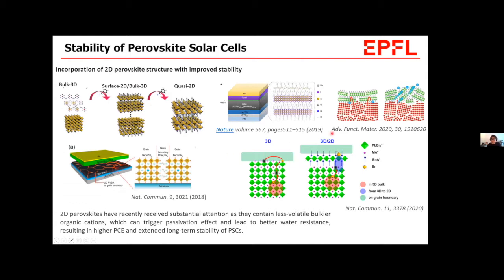So yeah, if we compare these two systems, 3D and 3D with 2D perovskites, about the ion migration, we can see the possible pathways of this ion migration in these two systems. So the diffusion barrier energy within this 3D work region would be similar in both systems. But however, the barrier energy for this ion diffusion becomes highly different when it comes to the region of grain boundary. In 3D perovskite, the ions can reach this grain boundary without being required to diffuse across the 2D perovskite barrier layer. So it's kind of a free path, it can just migrate.